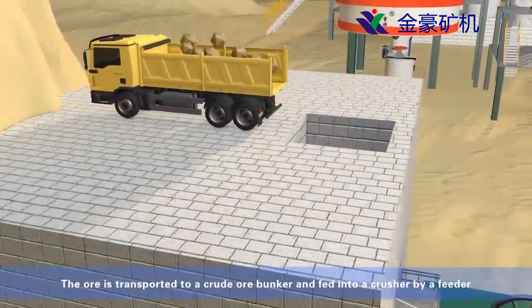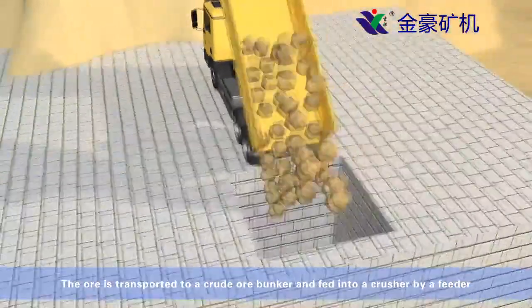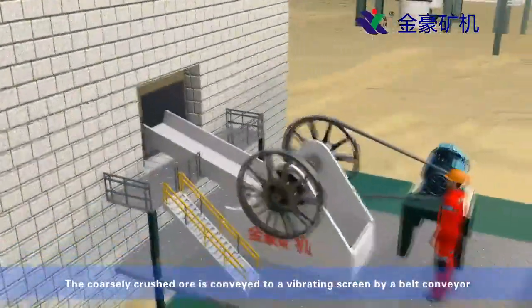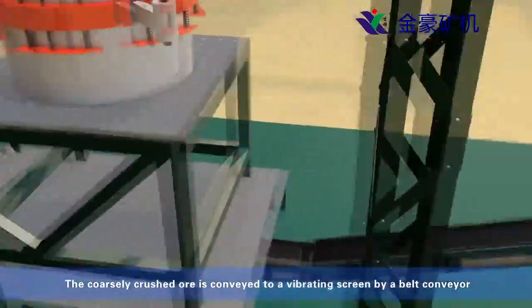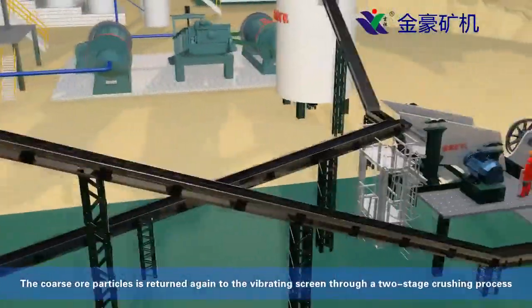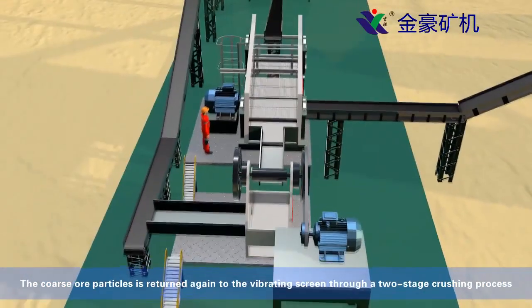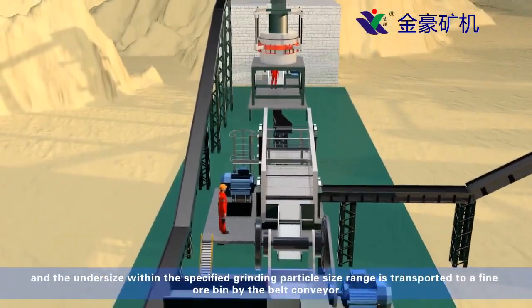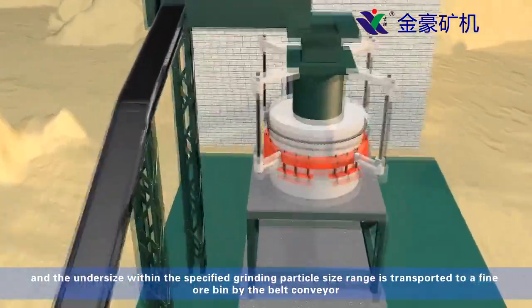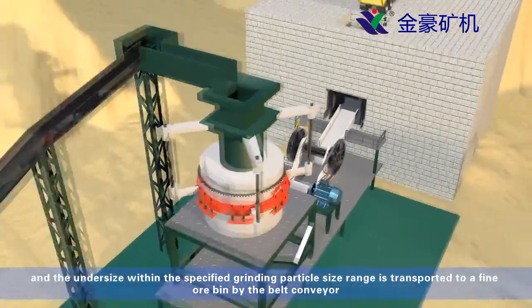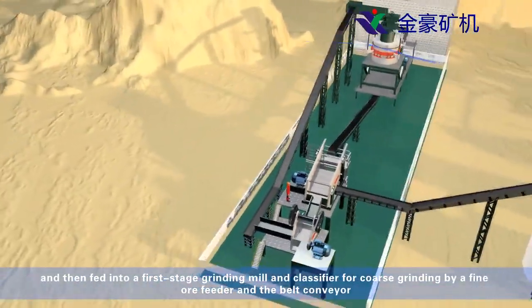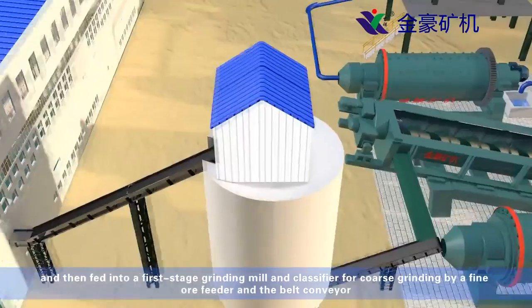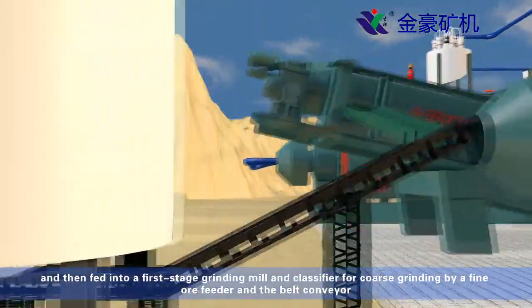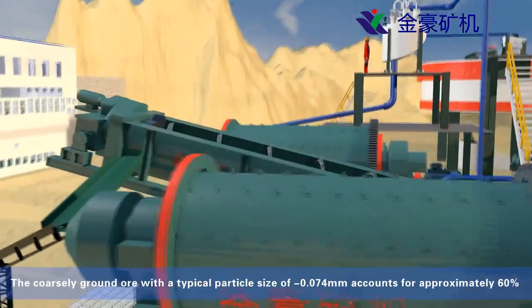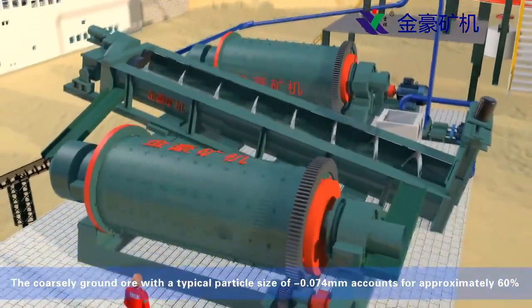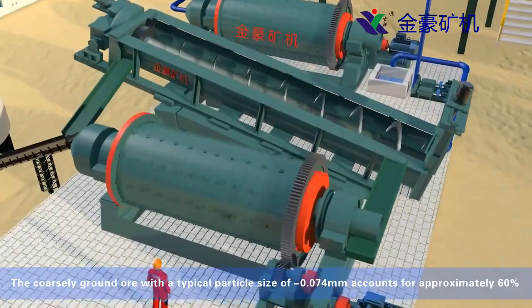The ore is transported to a crude ore bunker and fed into a crusher by a feeder. The coarsely crushed ore is conveyed to a vibrating screen by a belt conveyor. The coarse ore particles are returned again to the vibrating screen through a two-stage crushing process, and the undersize within the specified grinding particle size range is transported to a fine ore bin by the belt conveyor, and then fed into a first-stage grinding mill and classifier for coarse grinding by a fine ore feeder and the belt conveyor. The coarsely ground ore with the typical particle size of 0.074 millimeters accounts for approximately 60%.